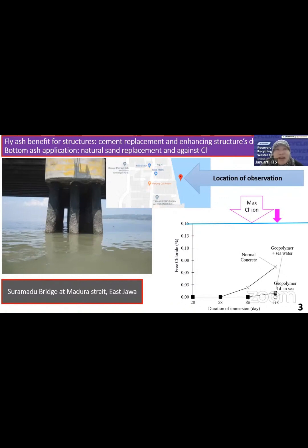We know that the fly ash and bottom ash have a lot of benefits for structures, especially to increase durability. Especially if we use geopolymer 100% to replace Portland cement with fly ash, it can enhance structure durability. And this picture was taken in one of the locations of piles in Suramadu Bridge at Madura Strait, East Java. You can see also here a lot of barnacles or biofouling attached to the piles. And we put our specimens very near here. We put our specimen, our geopolymer concrete, very near to the piles. Of course, these piles were made from conventional concrete.